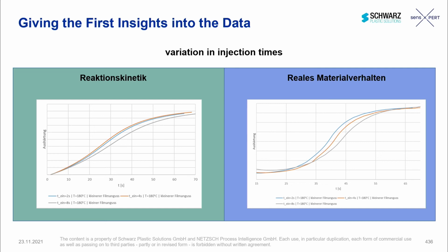So you can see that varying the injection times, in theory, there should be a shear change and therefore a different temperature state within the material that enhances the cure speed or lowers the cure speed. And that is what we can really measure, you can see here on the right side. But with pure reaction kinetics, like simulations are done today, or lab characterization, and then transforming the data with pure reaction kinetics to a process environment fails in this case, because here we cannot see the difference that really occurs.